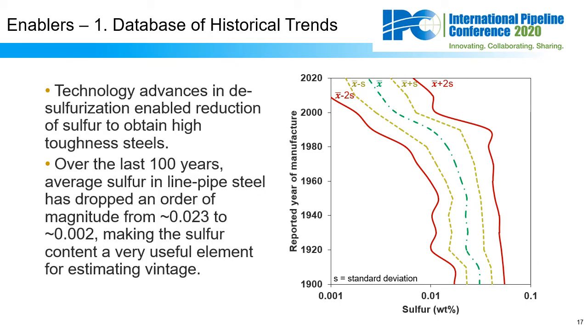Additionally, the distribution of sulfur has stayed fairly tight through the years, indicating that the entire line pipe making industry adopted sulfur reduction technologies somewhat uniformly as new technologies became available. So thanks to this tight distribution, the high sulfur steels from today are still lower in sulfur than the low sulfur steels from 100 years ago. Again, this dramatic decrease in sulfur content makes sulfur very useful for vintage estimation. So now that we've covered how historical strength and composition trends were our initial enabler of vintage suggestion, let's look at the NDE data that we need.